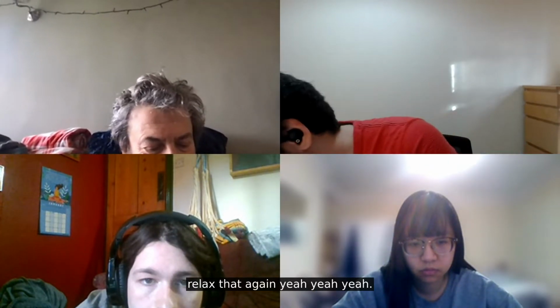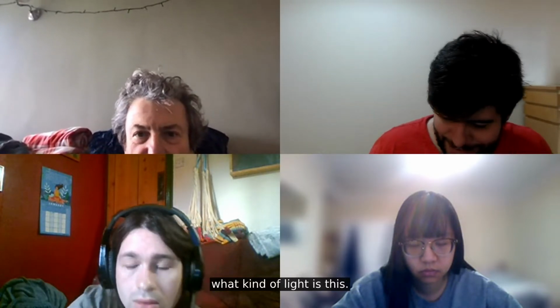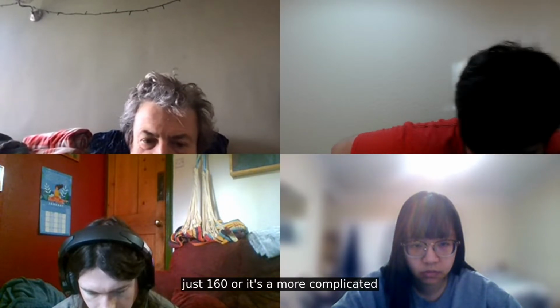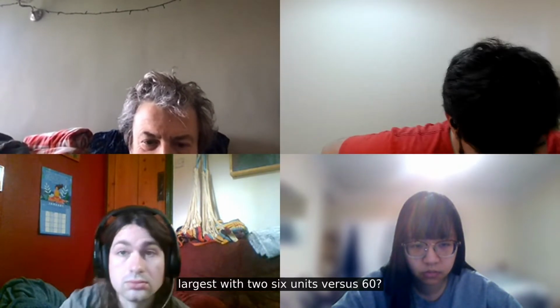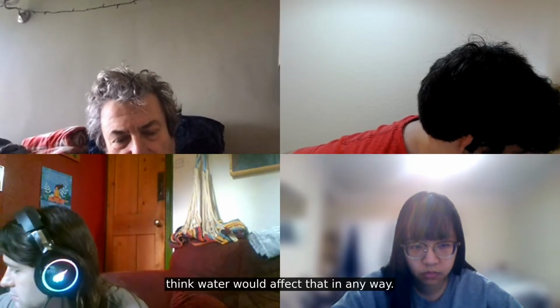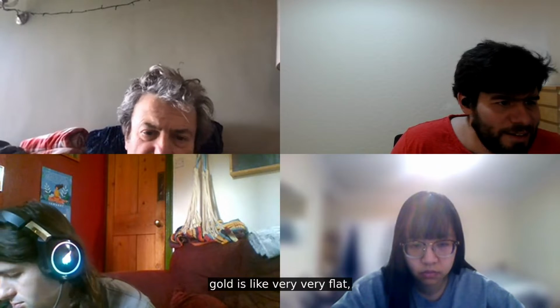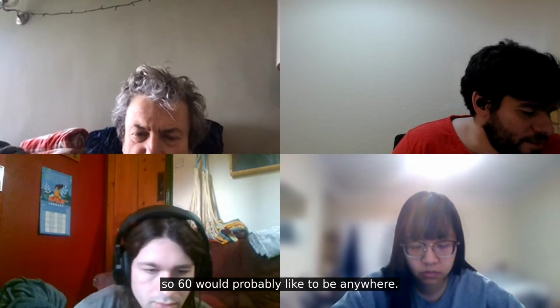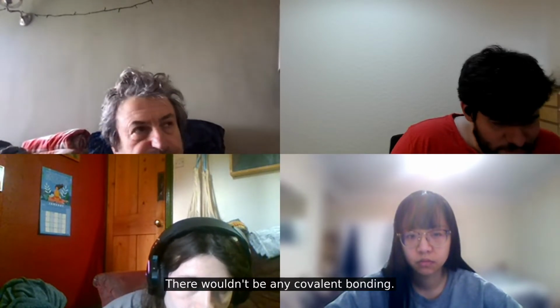Yes. And then you have to understand what kind of lattice this C60 would create. Would it be just one C60 in the unit cell, or a more complicated lattice with two C60? The unit cell where C60 would like to go. So maybe that calculation should be done without water, because I don't think water would affect how C60 stays on the surface. On the other hand, gold is very, very flat, so C60 would probably like to be anywhere. There wouldn't be any covalent bonding. It would probably be van der Waals interaction, which is a flat interaction.